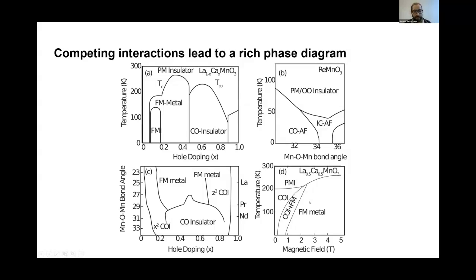So you can end up with phases where, to balance out the competing strain, you end up with some volume fraction of a ferromagnetic state and some volume fraction of an insulating state. I should mention that, at least at equilibrium, a lot of these phase transitions are first order. There's a change in the volume of the unit cell, and you end up with phase segregation being a very important aspect of the equilibrium physics in these systems. So since we know that the strain and the unit cell volume is very important to controlling the phase, we're going to use that in the first part of the talk.